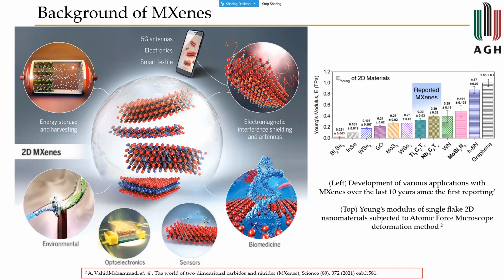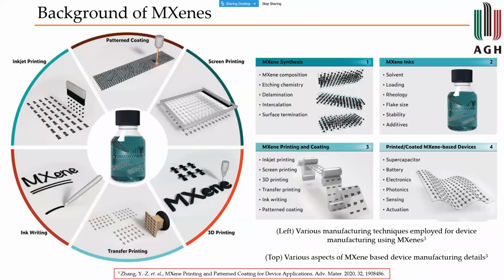And typically, a MXene 2D layer, which is a single layer of MXene, has a Young's modulus of about 330 gigapascal. These are comparisons between a similar type of experiment performed on the atomic force microscope. That gives you a comparison with graphene and reduced graphene oxide, etc. Our focus on MXene was also because of the processability. We could print them. Currently, we have made screen printed samples, inkjet printed samples, and also spin coated samples, which can be used.